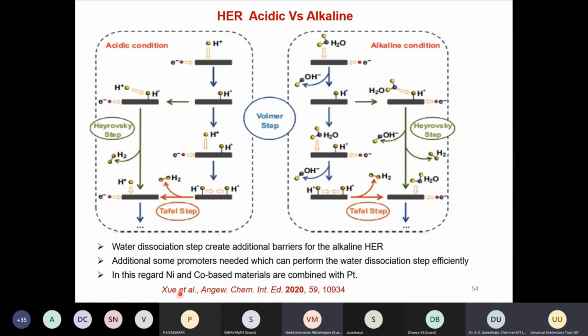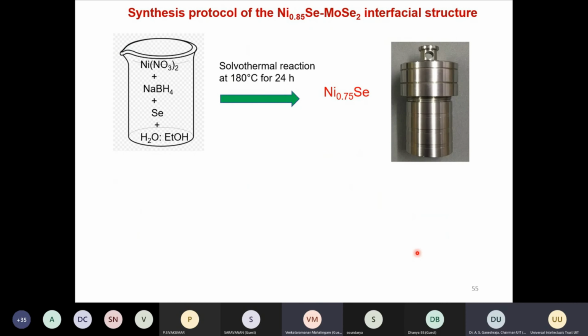So in this regard, nickel and cobalt based materials are combined with the platinum, because these two materials can do the water dissociation step, and then the platinum does the hydrogen evolution reaction step. So mostly the alkaline hydrogen evolution reaction happens in the presence of some kind of promoter. Okay. So our idea is to develop this nickel selenide molybdenum selenide.